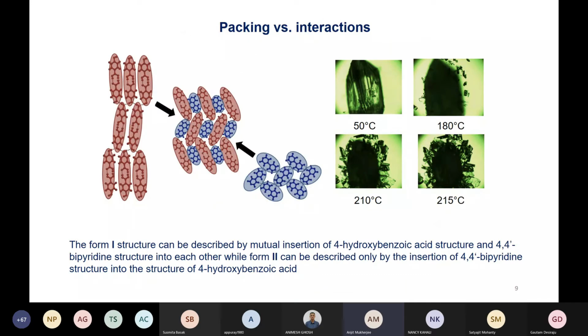And when we tried to investigate the packing of these co-crystals, we saw that in the form 1 co-crystals, it is just the addition. You can explain the packing of the form 1 co-crystals by addition of the native structures of the 2 compounds. And we also observed a very nice thing in the hot stage microscopy. When you try to heat it up, we saw the generation of form 1 crystals on the surface of form 2. So once again, this is one of the very basic things we consider in crystal engineering, the dichotomy between packing and interactions. And that is what is driving the synthon polymorphism in these cases.